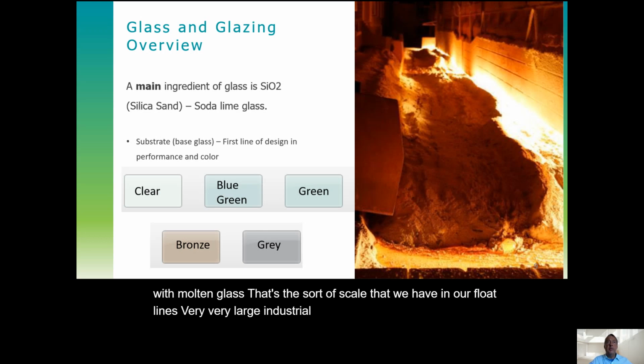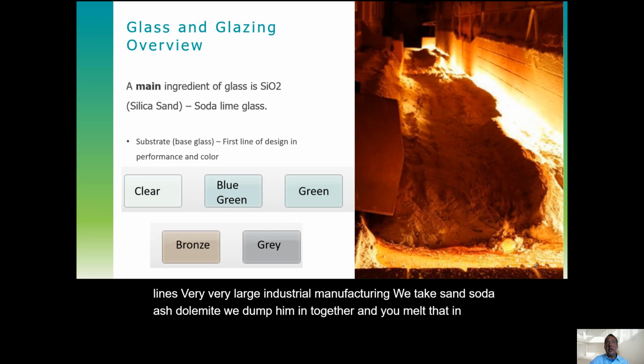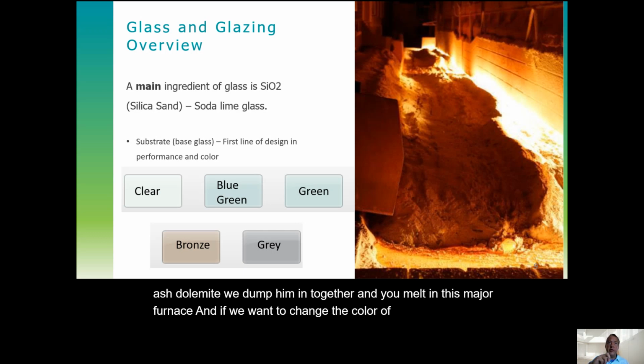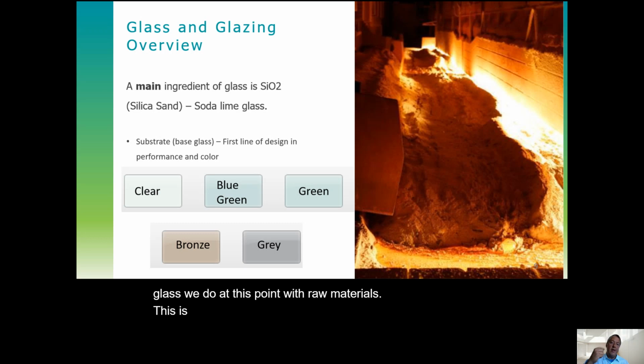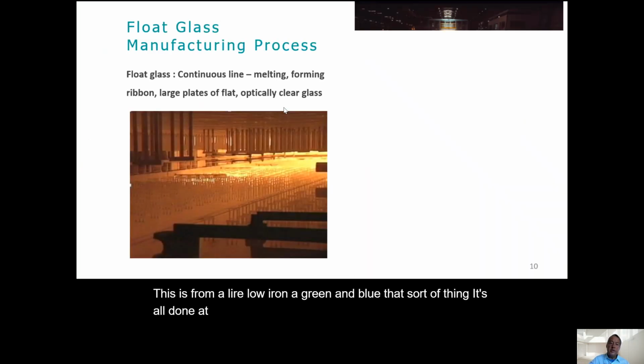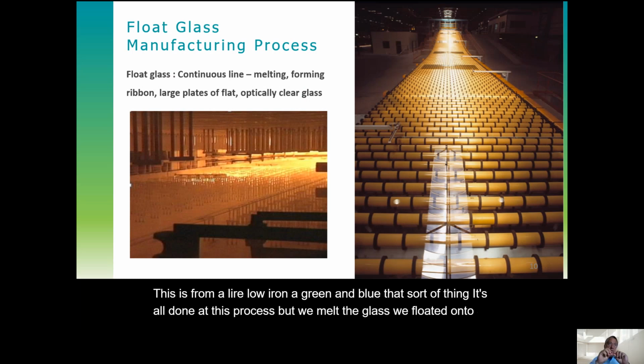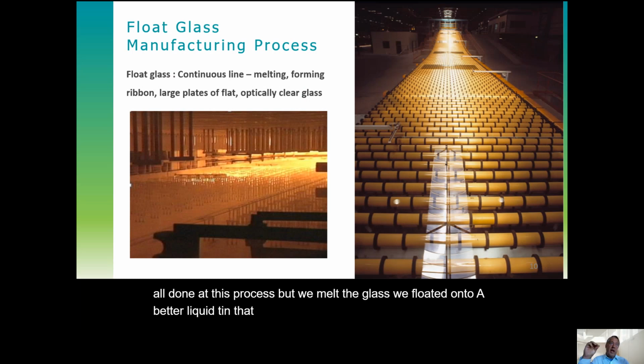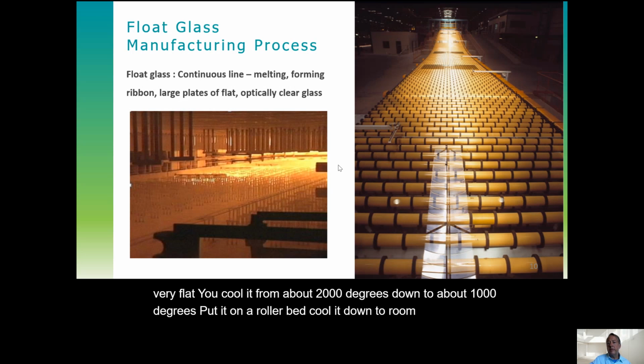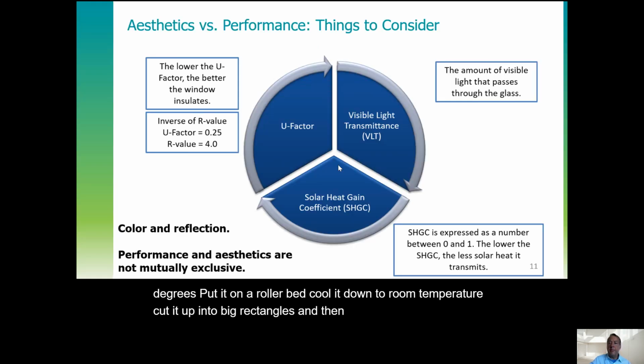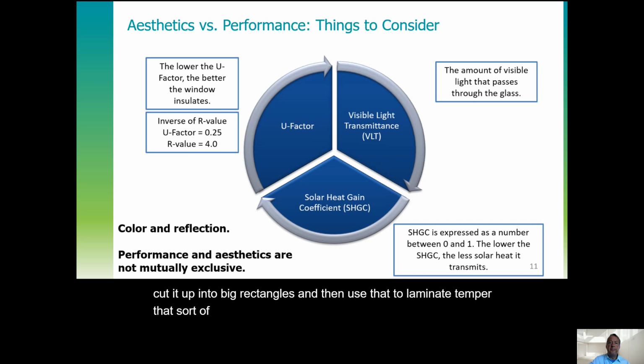We take sand, soda ash, dolomite, we dump them in together, and you melt that in this major furnace. If we want to change the color of the glass, we do it at this point with the raw materials. This is from a clear, a low iron, a green, a blue, that sort of thing. It's all done at this process. So we melt the glass, we float it onto a bed of liquid tin. That liquid tin makes the glass very, very optically clear and very flat. You cool it from about 2,000 degrees down to about 1,000 degrees, put it on a roller bed, cool it down to room temperature, cut it up into big rectangles, and then you use that to laminate, temper, that sort of thing. So we do a variety of things there.